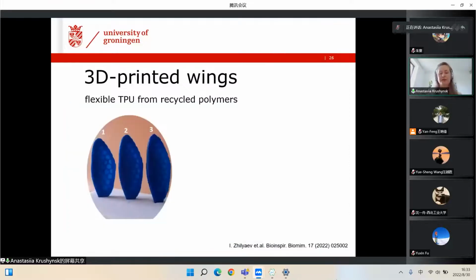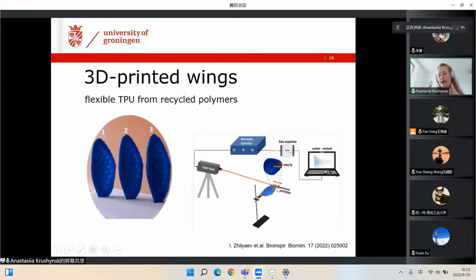Okay, so having printed these wings, we wanted to understand how accurately we can model them. And this is essential because, as I said, we use a low-cost 3D printer, so the printing quality is not very good. And it's important to know how many inaccuracies are introduced due to the manufacturing process. And for that, we tested the dynamic characteristics of the wing. So specifically, we fixed the base of the wing in a holder and excited it from one side manually by a hammer. And at the other side, by using the laser Doppler vibrometer, we measured the free-form vibrations. So basically, we hit the wing and then let it vibrate and then measure the vibration response.